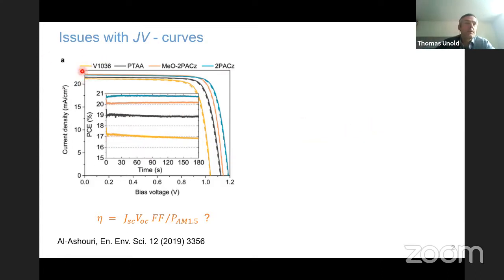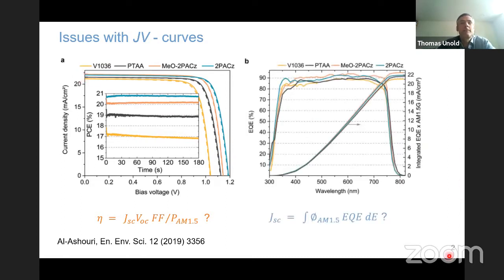And then also something that really happens is that the short circuit current is not totally correct. So one should really also check and report the short circuit current density that you get from the EQE when you integrate the convolution with the AM1.5 spectrum. So these are very basic checks, but as I said, I've seen it not only once in literature that this was not complied with.